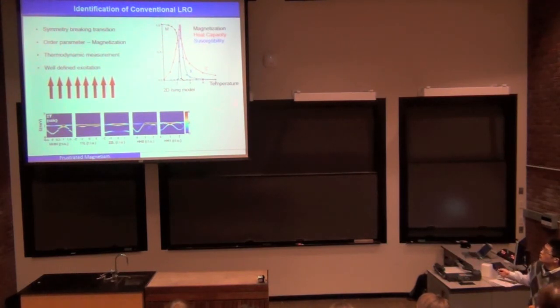So if you look at the two-dimensional Ising model as a function of temperature, the black curve shows you the magnetization. If we look at the magnetization as a function of temperature, there's a well-defined temperature where it turns on. And at the same time, we can look at other quantities that can be measured. For example, heat capacity. If we look at heat capacity, it shows a divergent behavior at exactly the same temperature where the magnetization turns on. So those all point to a well-defined phase transition point. And the behavior of susceptibility can also be used to define this long-range magnetic order.